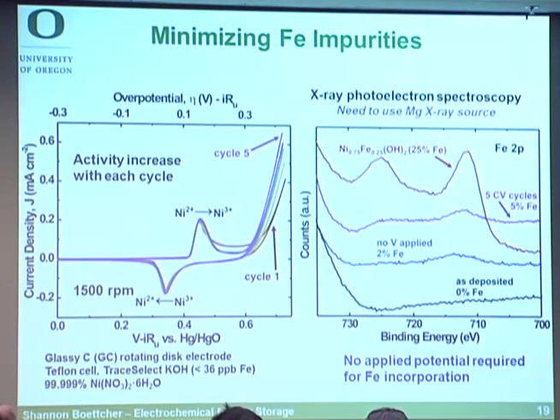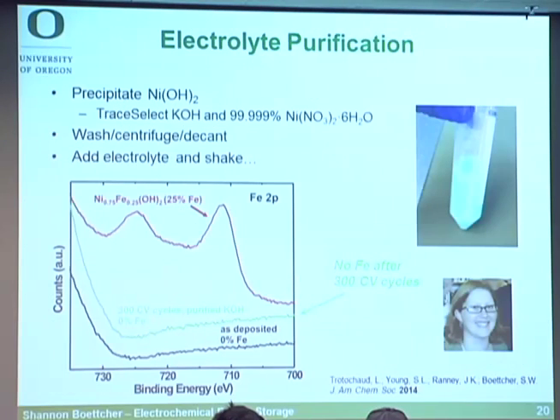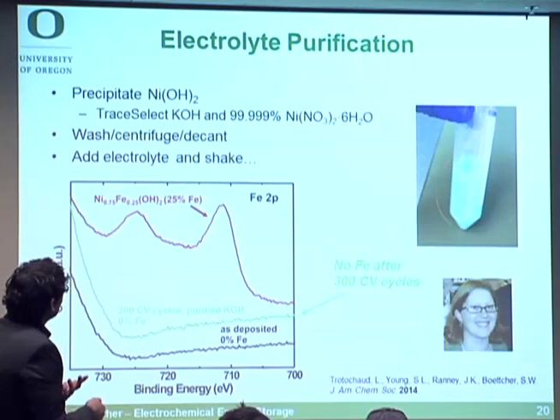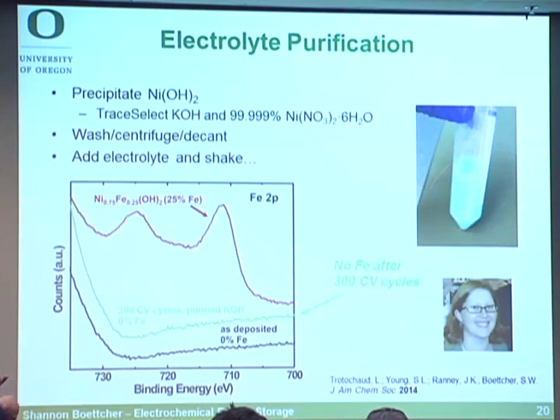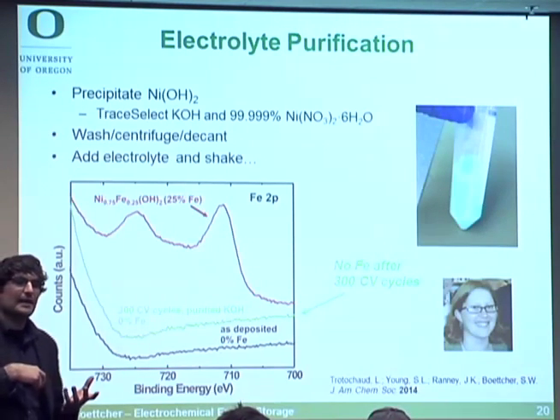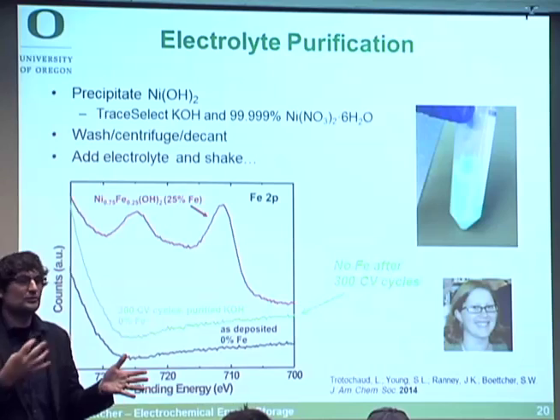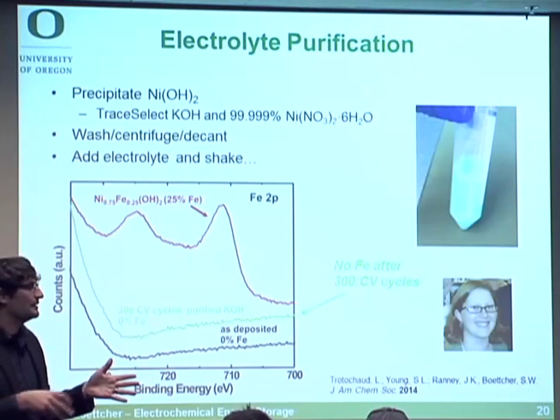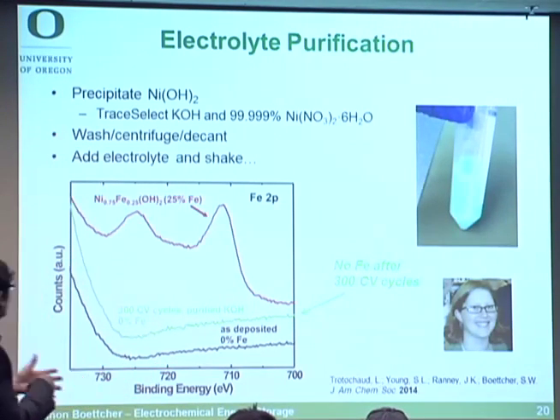So how do we get rid of this? Well, what Lena figured out, came with a nice idea, is that if the nickel hydroxide with no potential applied sucks up iron with high affinity from the electrolyte, let's use that to purify the electrolyte. So what she does is she precipitates nickel hydroxide and shakes her electrolyte in a test tube, centrifuges, decants, and uses that electrolyte to test the catalyst in thin film. So she uses a catalyst in powder form to purify electrolyte that then is used to test the catalyst in thin film form. And now you can cycle forever and you never get any iron in. So now you have a really good control sample. So this was really important.